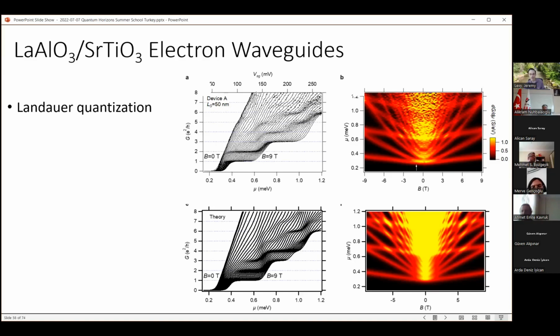And so you can then take this curve, turn it into this one, and compare it with experiment, or usually the other way around. We adjust parameters like effective mass and so forth to match what we see experimentally. But the fact is that we can account for all of the lines that you see here, all of the subbands.